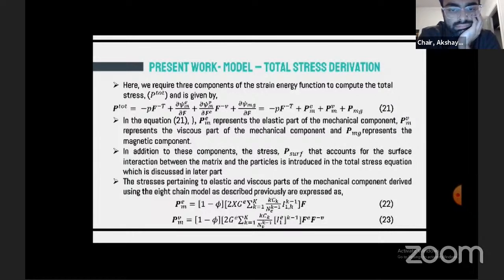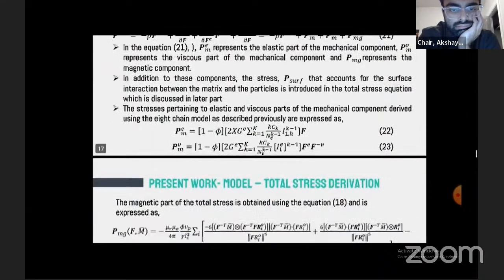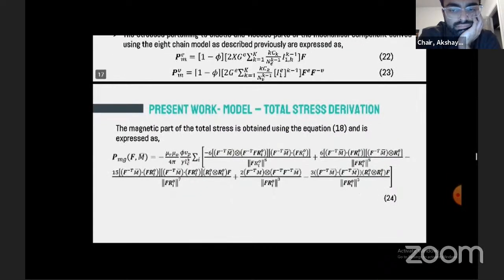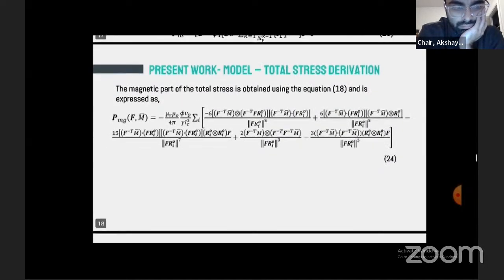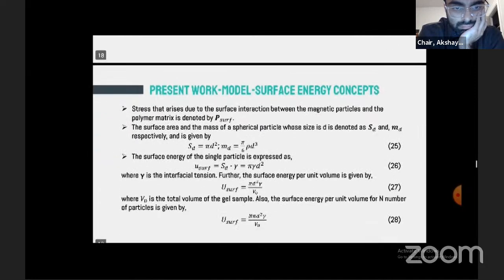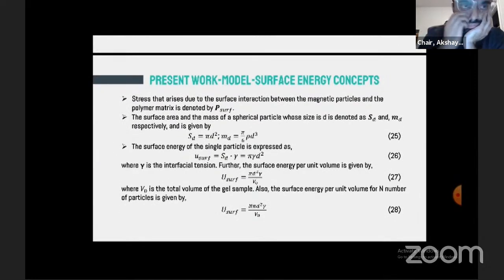The stresses pertaining to the elastic and viscous parts of the mechanical component using the 8-chain model, as described previously, are shown in equations 22 and 23. Similarly, the magnetic part of the total stress obtained using equation 18 is expressed as follows in equation 24. So now we'll go into the surface energy concepts. The stress that arises due to the interaction between the magnetic particles and the polymer matrix is denoted by P surf. Generally, the surface area and the mass of the spherical particle whose diameter is d are denoted by Sd and Md and given as shown in equation 25.